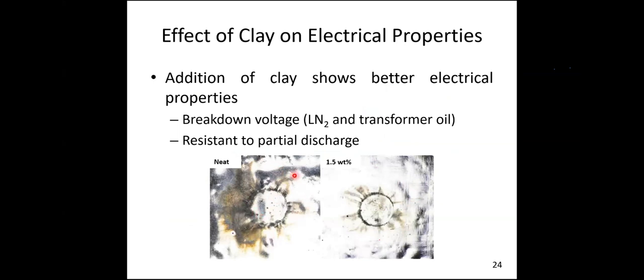If you see the photograph of the neat epoxy without clay, there is major damage, whereas on the right hand side, the 1.5 wt% clay epoxy shows minimal damage. So because of clay, the breakdown voltage is increased with the addition of clay in epoxy. This is what we have found from the electrical properties of epoxy clay nanocomposites.